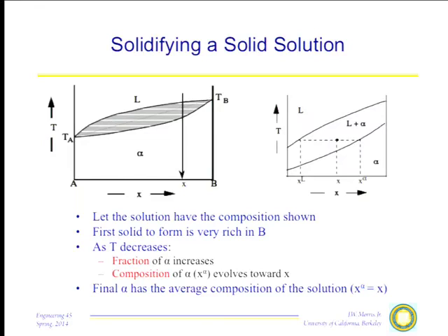Well, let's consider what happens as we solidify a solid solution. So we're going to start up here in the liquid phase at this composition that I've shown here in the left-hand plot in the figure here. And I'm now going to cool at that constant composition. As I cool, nothing happens until I hit what's called the liquidus curve, the upper end of this two-phase region right here. As soon as I do that, some solid is going to start to form.